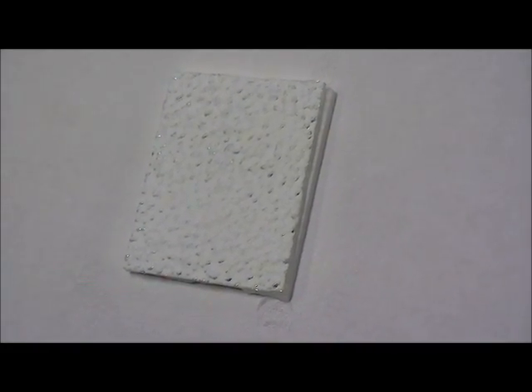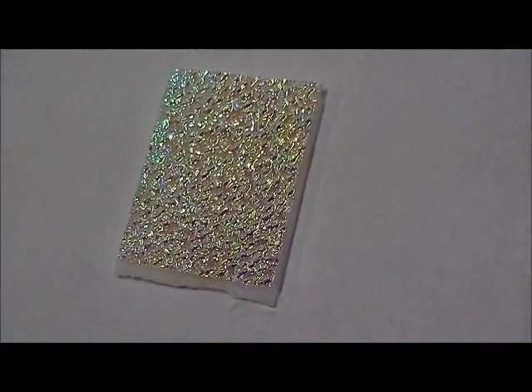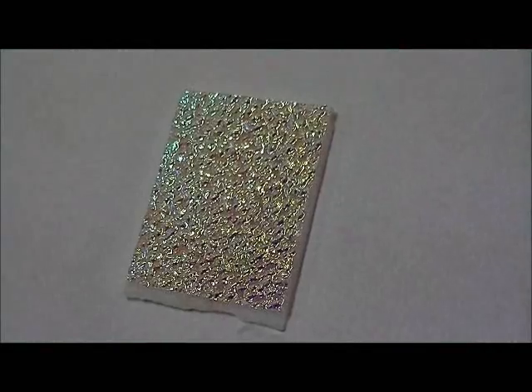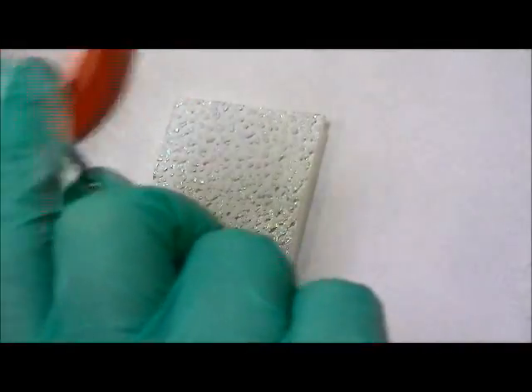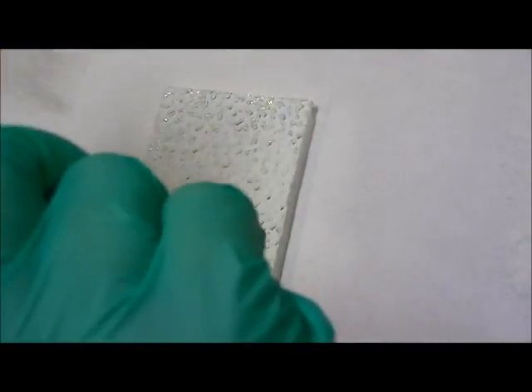This leaves the thinnest layer of clear on top, and that's good, because what we need to do, guys, is we need to actually chemical etch this when it's fused and make that glass a porous surface, okay? So if you chemical etch the top of the raw dichroic and skip that process, what would happen? You would take all of your dichroic off. So the clear powder is your buffer, isn't it? Okay? All right, so we have a very thin layer.